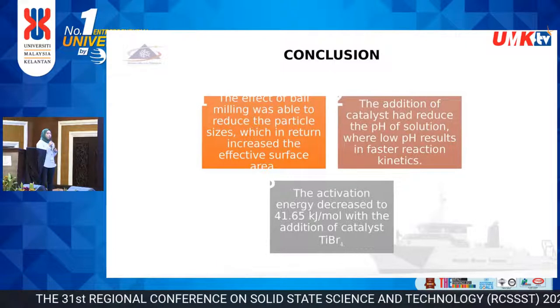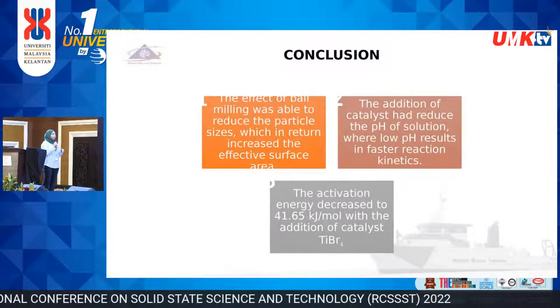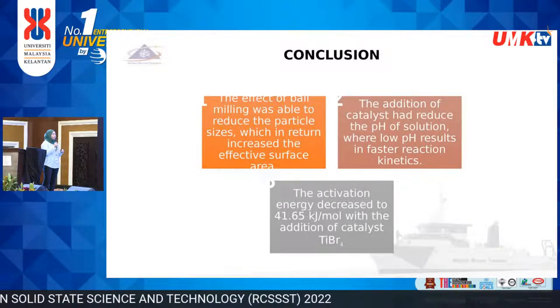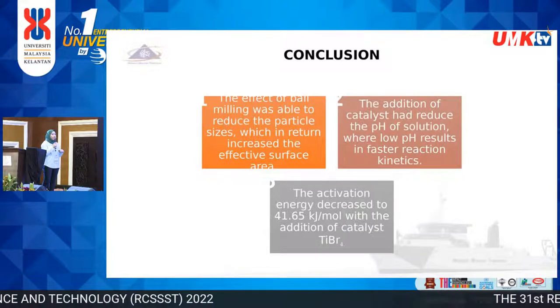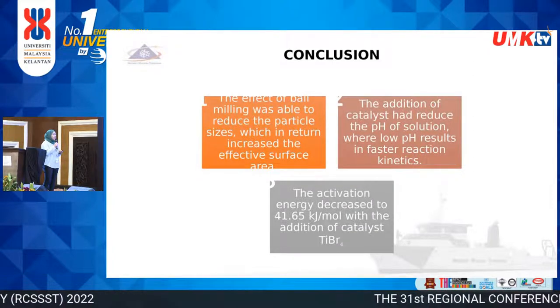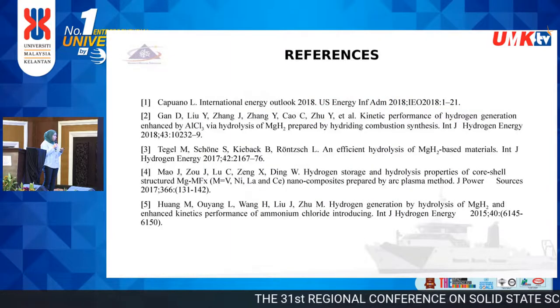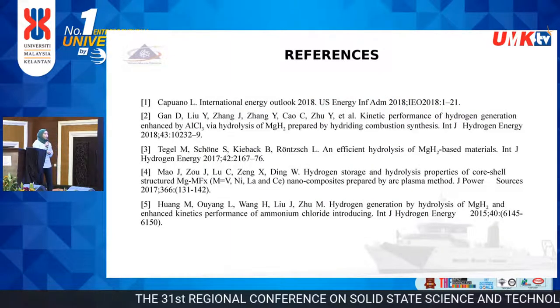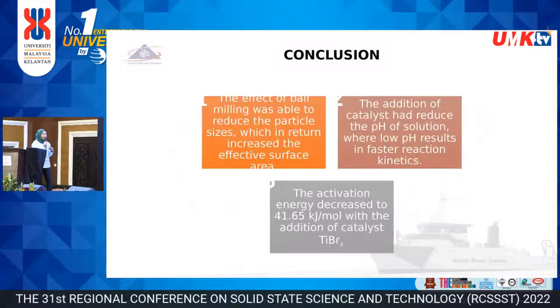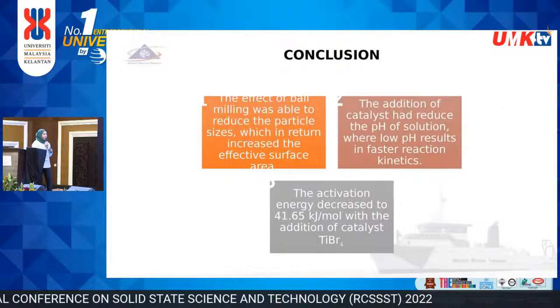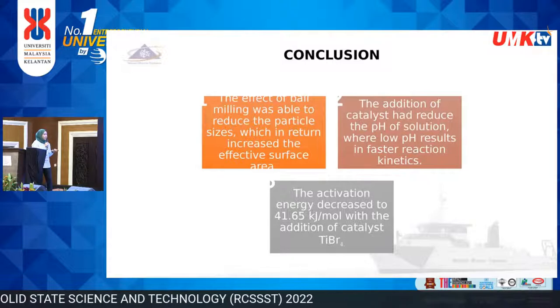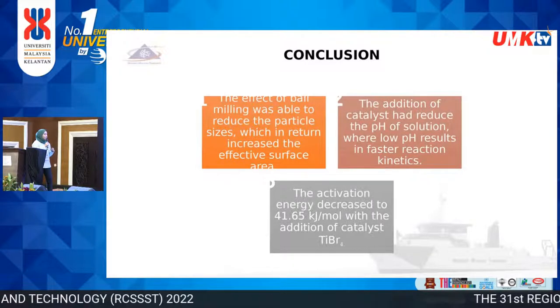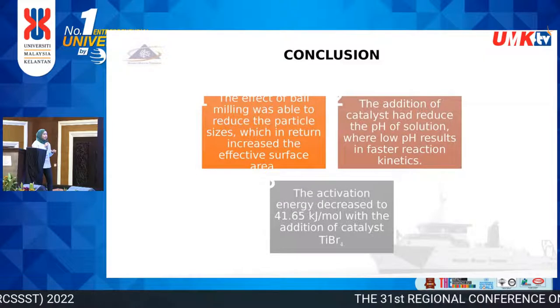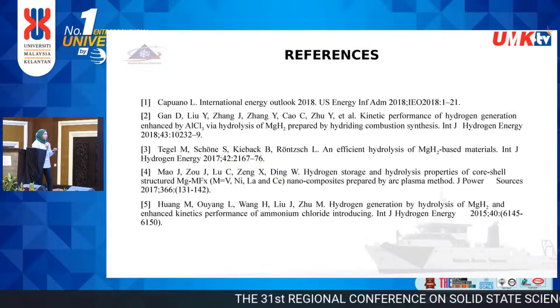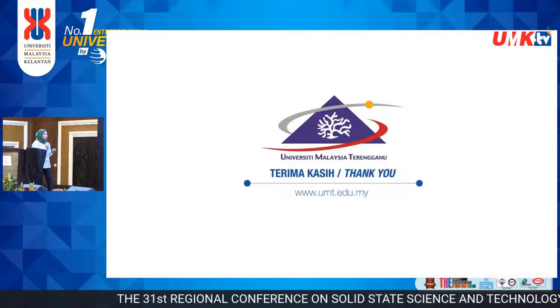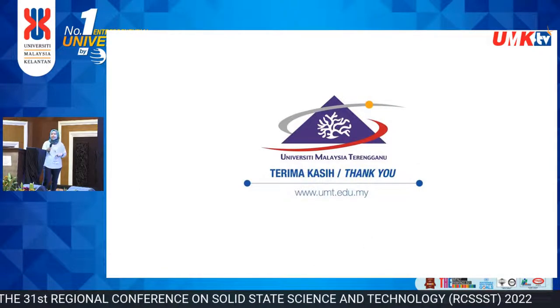So in conclusion, the effect of ball milling was able to reduce the particle size and in return increase the effective surface area. And secondly, the addition of catalyst has reduced the pH of the solution, where low pH can result in faster reaction kinetics. And last but not least, the activation energy has decreased to 41.65 kilojoule per mole with the addition of the catalyst titanium bromide. These are my references. That's all from me. Thank you.